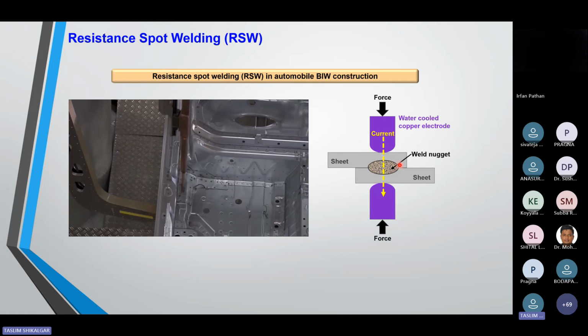But automotive industry observed some major disadvantages, because during this type of welding, zinc is coated above these two sheets, and because of this current and because of this temperature, zinc is vaporizing, and after this vaporization, zinc is directly going inside the sheets, and because of the zinc, additional cracks are going to develop. So automotive industry is finding a solution for how we can utilize this methodology without generating the zinc cracks.